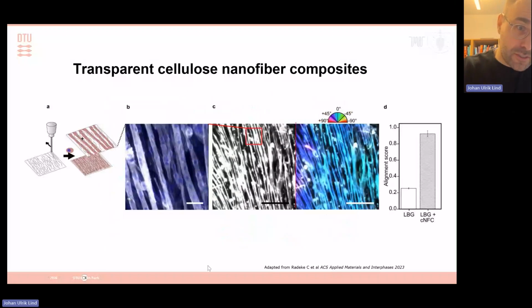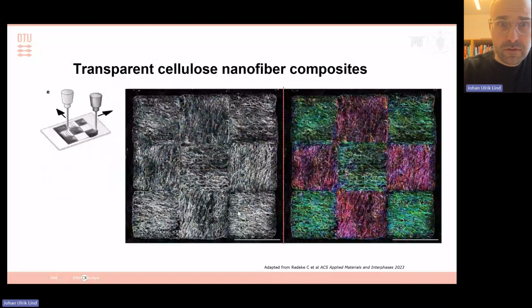So then we were interested in seeing, we know that these nanofibers should align with shear as we print. So essentially, we put the fibers into the gelatin inks I showed you before. And what that means is that the local stiffness will be different along the fibers and transverse to the fibers. And what we found is that that was very efficient in aligning the cells. We get beautiful skeletal myofibers. We can culture those for months. And what we can also see is that they follow local orientation very well.